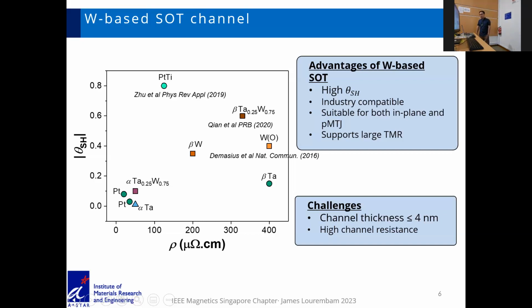tungsten is the more suitable choice here, because it can support both in-plane and out-of-plane magnetic tunnel junctions. For example, platinum cannot support out-of-plane magnetic tunnel junctions, and it has a pretty large TMR, which means the read signal is high. However, the tungsten film typically likes to be in the alpha phase, which has a low spin Hall angle. So the challenge here is that the channel thickness on these kinds of deposition tools is limited to 4 nanometers. So we want to widen this thickness transition window. And the other issue, of course, is the high channel resistance.